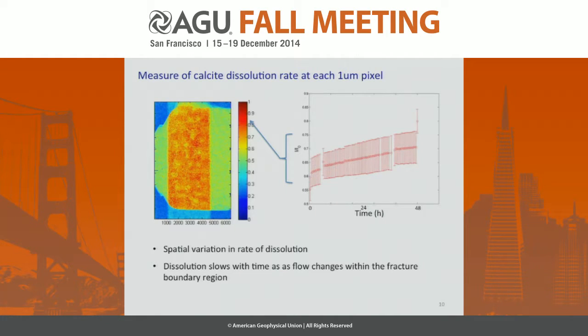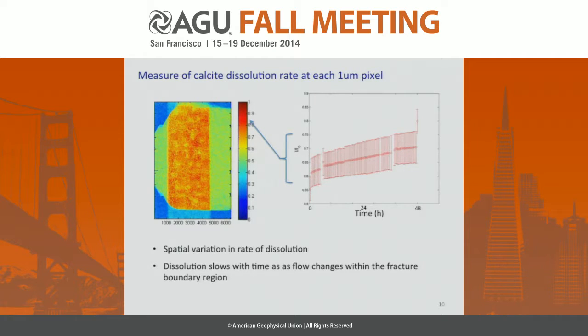The ultimate goal of this method is that we're able to look at the calcite dissolution rate by combining information about how much calcite has been dissolved and how much silicate was left behind. What we observe is that over time the dissolution rate slows as this porous network develops. This spatial variation is related to a complex combination of both flow and mineral distribution.